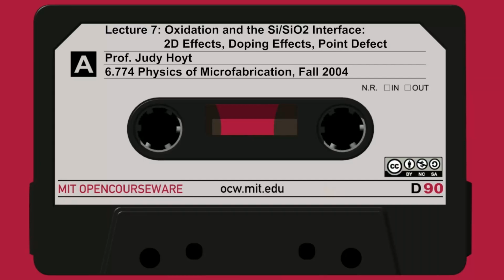This G is meant to represent the generation of interstitials, or the injection. It's a certain rate of generation of interstitials that get injected and then go into the bulk. Here they are. Here's an interstitial. There's also a flux of interstitials from the bulk to the surface, and they can recombine. So interstitials can be generated during oxidation. They can also find their way to the surface, and they can recombine there. The interstitials can recombine in the bulk with a vacancy. They can find a vacancy and go away. They can diffuse over to this surface, which is a non-oxidizing or inert place, and recombine. Or they can go into the bulk, and here's a buried dopant marker layer, which started out looking like this dark green.